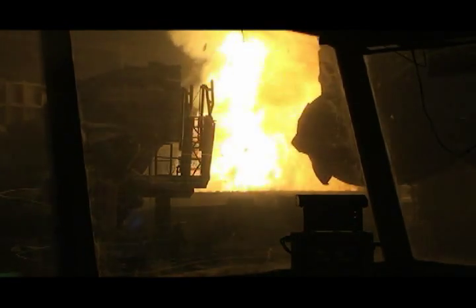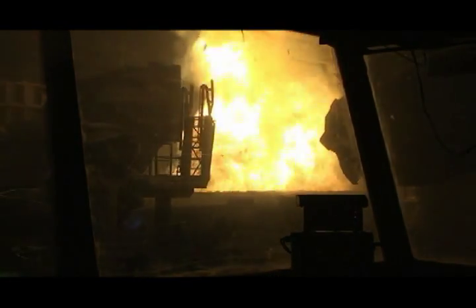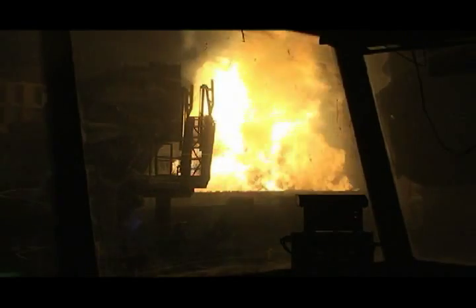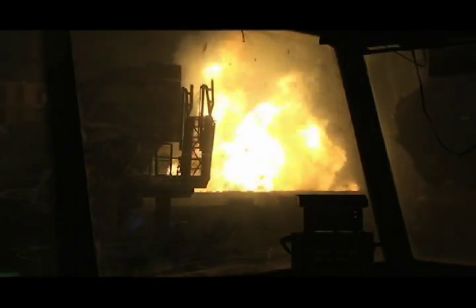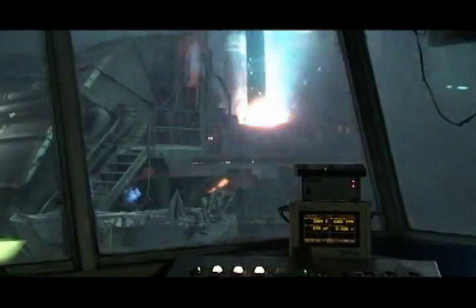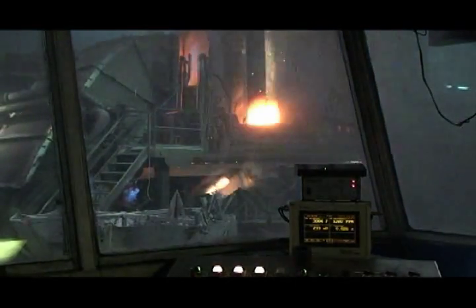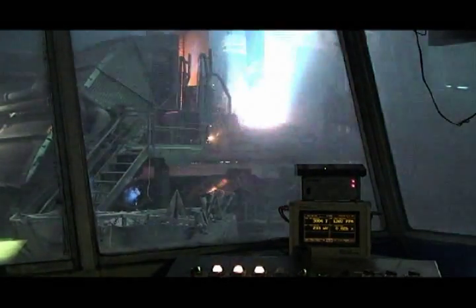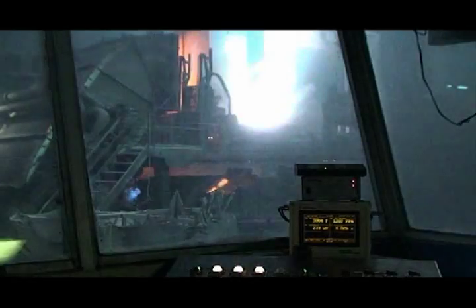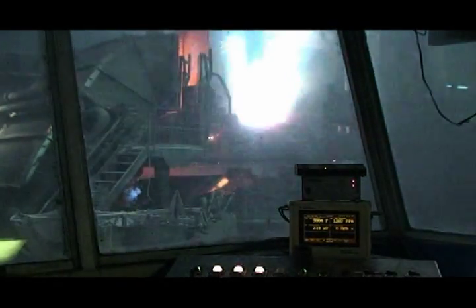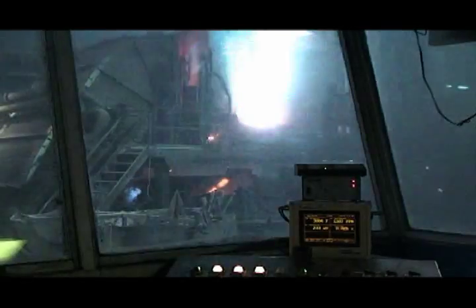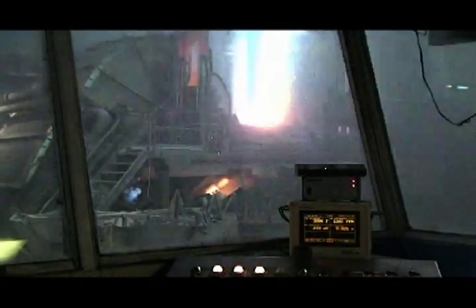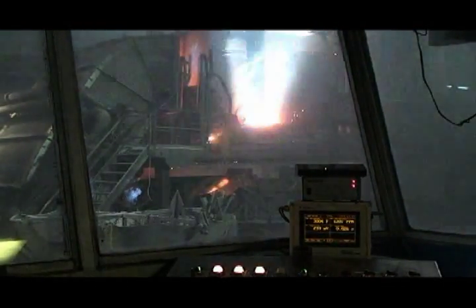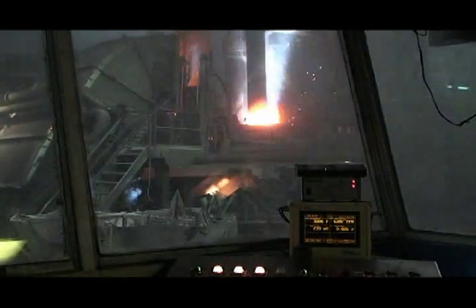The first charge of scrap weighing 140 tons is charged into the electric arc furnace. Power to the scrap buckets is distributed from a transformer to 3 arms that each conduct current. Each arm holds a 24-inch diameter electrode, applying 75,000 amps per phase of electricity to melt the scrap. 1 minute of electricity usage is enough to power an average home for a month.